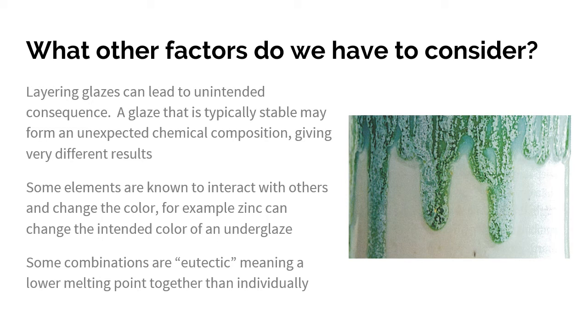You also have to be careful that when you mix two glazes together, you now have a different combination of fluxes, which means things are going to melt at different rates. So it's possible to have a eutectic layering of glaze, basically a synergistic effect where the overall melting point is lower than any individual glaze component. This is just a picture of a layering of 3 different glazes. As it melted, the glaze on top melted at a lower temperature and really ran on the piece. As an artistic decision, it's beautiful and can be intentional. And then sometimes you end up having to chisel your piece off of the kiln shelf because you had a little too much running. That's why it's always good to make a test tile, especially with new glazes, to see how they work in combination.